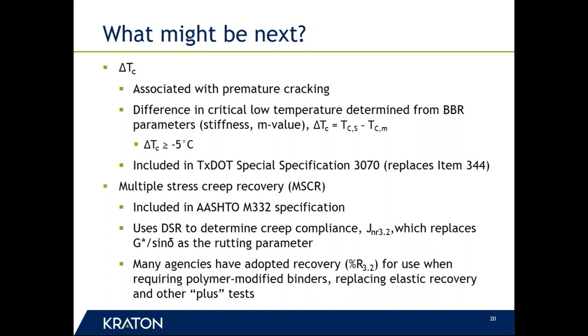Another thing that comes out of that test is a percent recovery, where you're able to see how much elasticity you have in the material. And that is something that in many states is being used to replace the elastic recovery that I mentioned in the slide that showed the specification, because this takes much less time to run. There's much less variability in it. It's just an easier and more indicative test to run that looks at the effectiveness of modification on the asphalt binder.